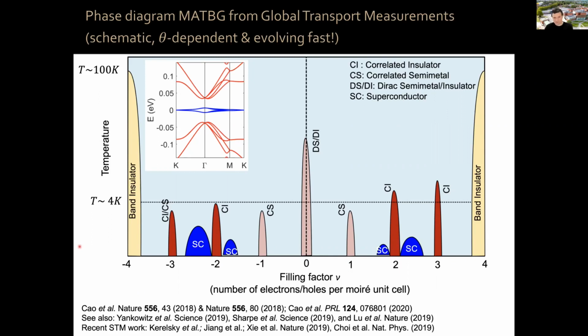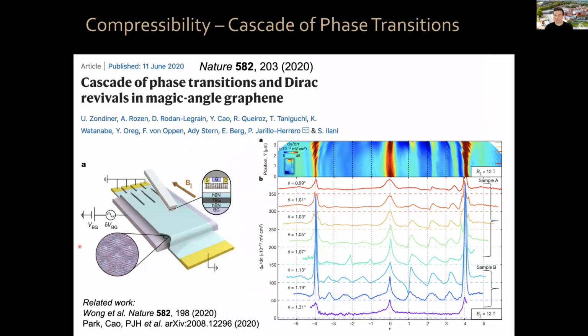Now, the other thing that I want to tell you, which is quite important for bilayer, is that last year, in a paper in collaboration with Shahal Ilani at the Weizmann Institute, and similar related work by the group of Ali Yazdani at Princeton, we realized that there is this cascade of phase transitions, we called it, in magic angle twisted bilayer graphene, as you go through each of these integers, 1, 2, 3.